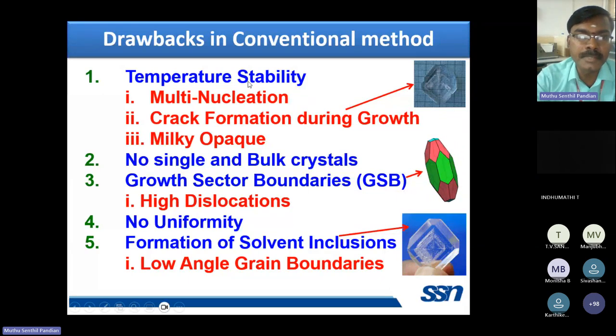So these are some of the disadvantages when we grow the crystal by this conventional method. Due to temperature instability, multinucleation will be formed in the conventional method. Microcracks will be formed during the growth. There are a lot of micro-phases also formed in the conventional method grown crystal. And we cannot grow single and bulk size single crystals in the conventional method. Because of the grain boundaries, more number of grain boundaries in the conventional method, the dislocation density of this conventional grown crystal is always very high. This we can easily identify using chemical etching and HRXRD measurement.